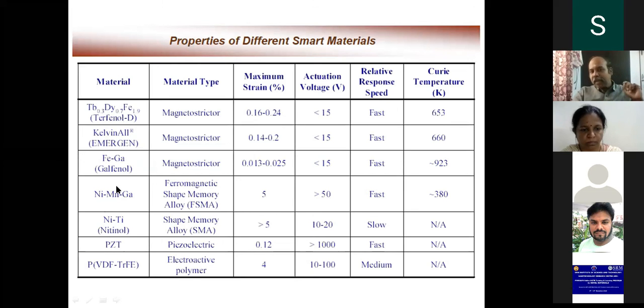But when we compare with the shape memory alloy, you see in the shape memory alloy the magnetostrictive strain we get is about 5%, which is much superior to magnetostrictive material. But the only problem here is the magnetic field required is very high. You have to apply several Teslas of magnetic field to produce this, and also the material should be a complete single crystal for showing such a high shape memory effect.